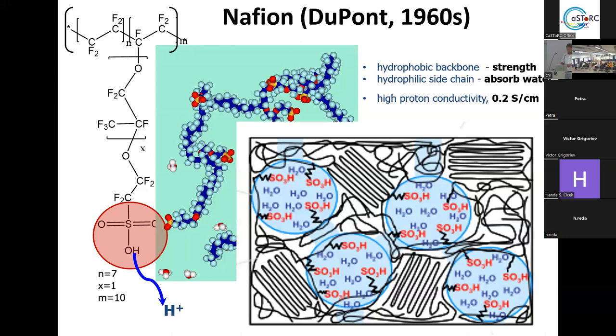Inside the water micelles you have water, counter-ions, and hydronium ions H3O+. These micelles are connected by water channels — there is much debate about whether these channels look like elongated cylinders of uniform thickness. The material is a semi-crystalline polymer with crystalline domains connected by amorphous parts, making it a very complicated and heterogeneous macroscopic structure.